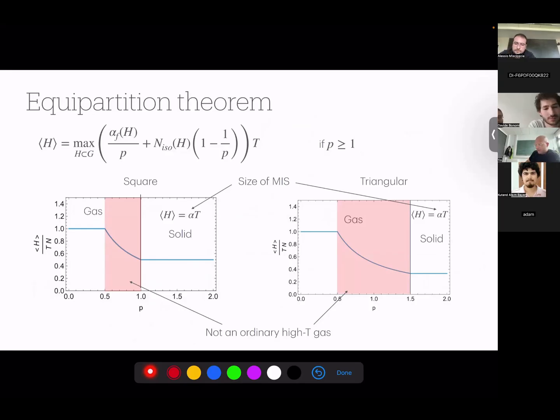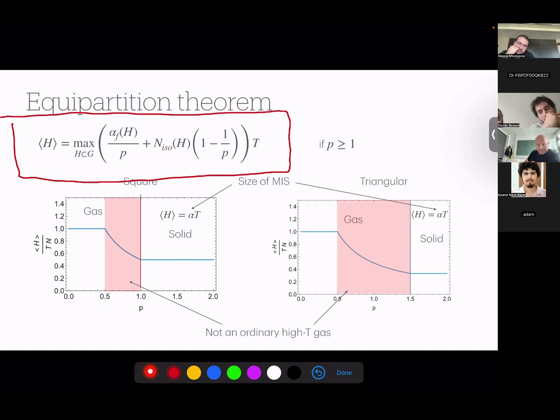Good. Now, even before proving that order happens, what I want to emphasize is that you can show, by using this dominant configuration, that the equipartition function looks something like this. That means that at very high temperature, your average energy is proportional to temperature, but there is some complicated coefficient here. And if P is small enough, you can show that this coefficient is just 1. This is what you usually expect from normal gases. If temperature is very large, then all of these sites behave independently. There's n degrees of freedom. This is equipartition divided by n, so this should be 1. The coefficient should be 1 times n.